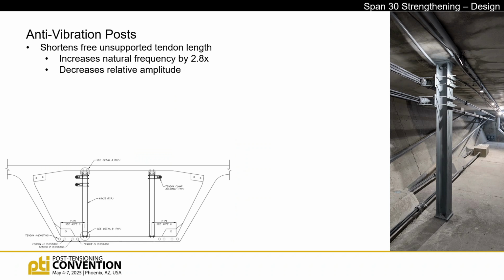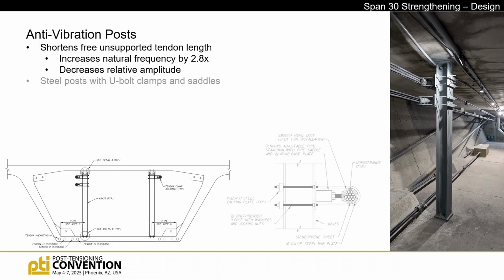All right, we had long, straight tendons, so they don't go through deviators, so we needed to deal with the vibrations here. We did a vibration analysis that showed that basically we could support these on about a 40 to 50 foot spacing to prevent any issues. For the steel, we used steel posts that had basically just U-bolt clamps and saddles.